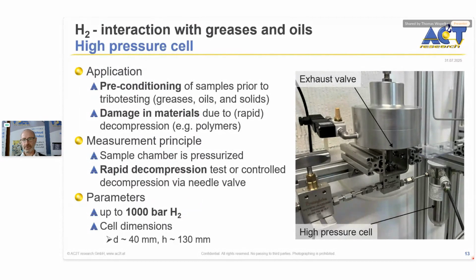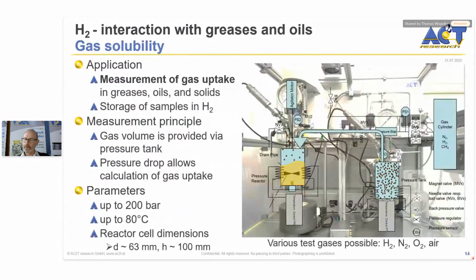We can do a rapid or controlled decompression via needle valve, and this is interesting because you can test the destruction of polymers due to rapid decompression tests, for example. The cell can be run up to 1000 bar. The cell dimensions are quite small, so we can store only a very small test specimen in this high pressure cell.